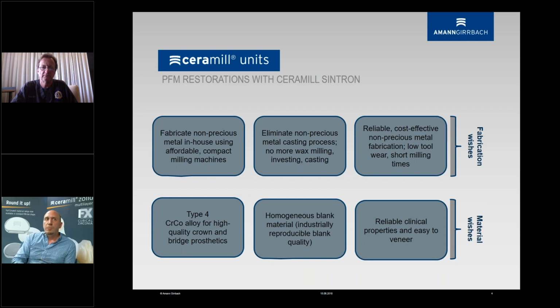And once you open the chamber system and look at the finished sintered result, you should have a silver color, maybe with a little bit of red hue, silver, almost golden look to it. And then you can go straight on sandblasting, steam clean it, bonding agent if needed, and opaquer on it. And then you should be good.